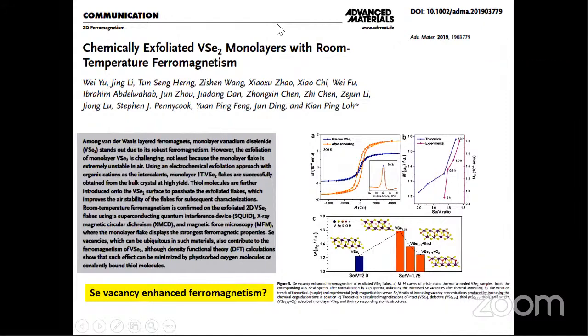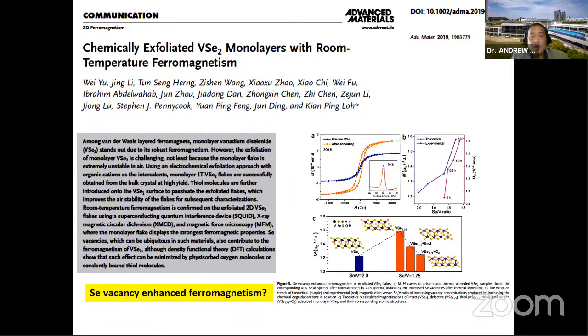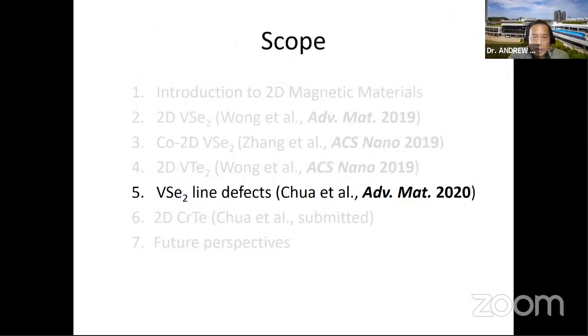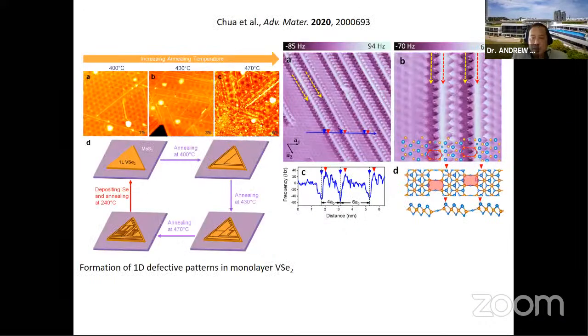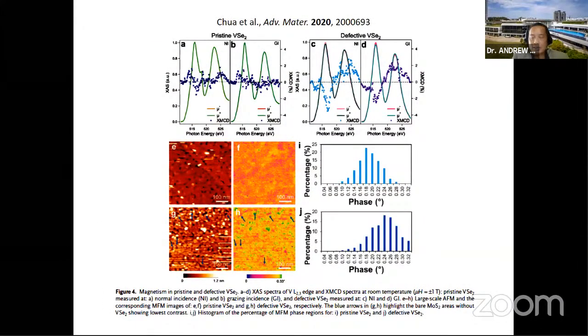Now, as you can see from our work, we showed that a perfect vanadium diselenide film is a frustrated magnet. That means in our view, it is not magnetic. But to make it magnetic, we have to introduce anisotropy, which in our case was introducing defects, which I showed here. By introducing defects, we measure magnetic signals. And hence, to answer your question, if it's perfect, there will be no magnetism, just for this case of vanadium diselenide.